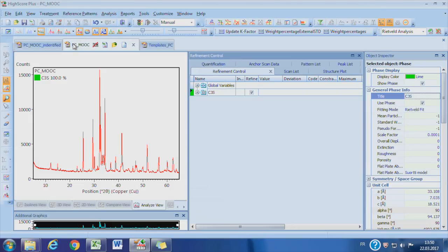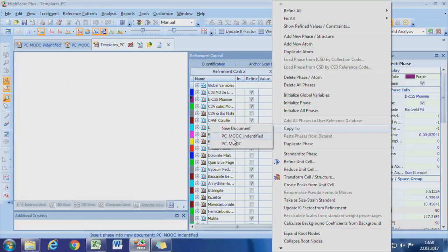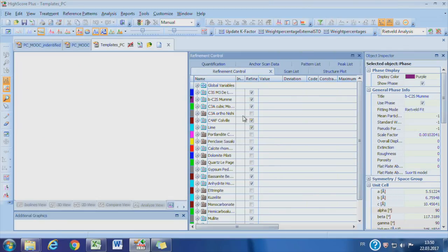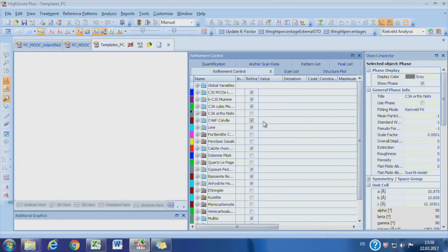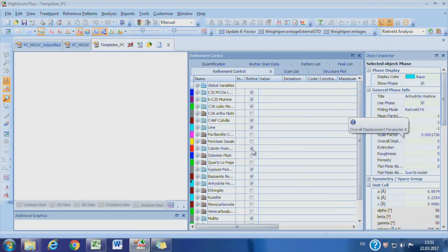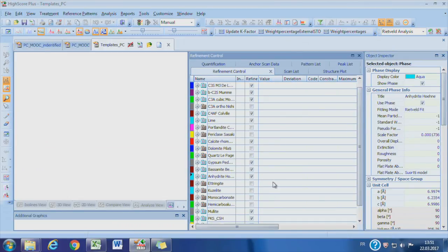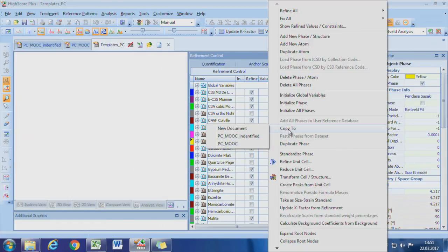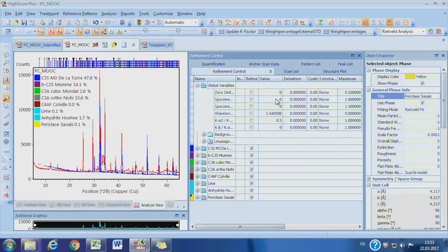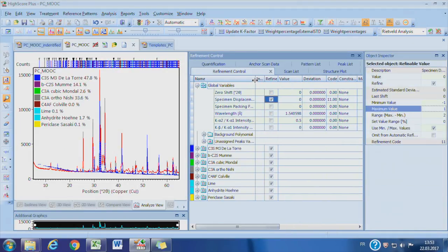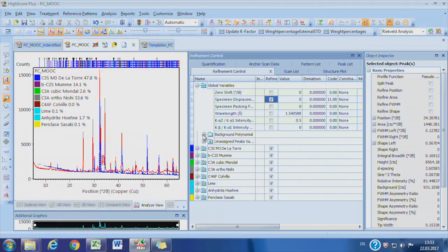We keep the two most common polymorphs for C3A, namely the cubic and orthorhombic ones. Alternatively, if you already have an HPF file with all the phases, you can copy the phases from one HPF file to another by right-clicking the phase and copying to the new HPF file. When all limits and parameters to be refined are set in the template HPF file, check all the parameters for the phases. Then set the global parameters: specimen displacement and background functions are usually refined. Polynomial functions with five coefficients were used for the background. We use manual mode for refinement as all refinement parameters were set manually.